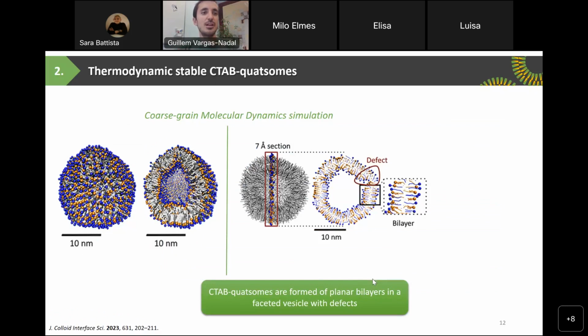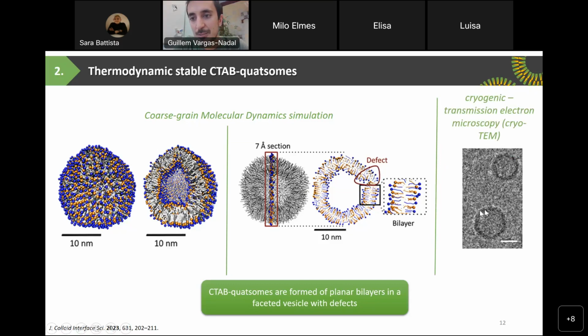And here I want to show you, first of all, how we know that these quatsomes are thermodynamically stable. In this case, some molecular dynamics simulations have been carried out, coarse-grain simulations, which allow us to simulate a whole vesicle. And in this case, you can see that they have some defects in the membrane. So they are not spherical. They have some defects, and these defects can also be seen in the cryo-TEM images, where you can find some planar layers. So these defects are what make the quatsomes thermodynamically stable.